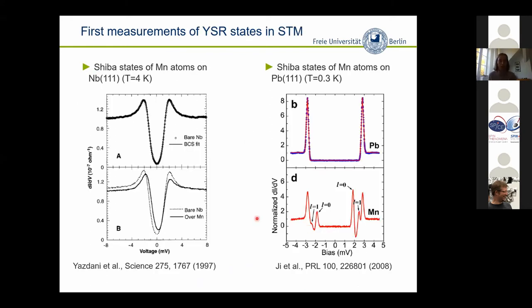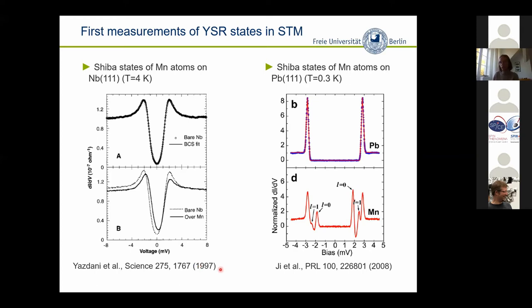We are not the first to measure Yu-Shiba-Rusinov states on single atoms — it dates back more than 20 years. Ali Yazdani and the Eigler group looked at manganese atoms on a niobium surface, using a metal tip at 4 K. Measuring on the bare superconducting surface gives an expression of the superconducting energy gap and the onsets of coherence peaks. When measuring on a manganese atom, they found an asymmetry and a slightly smaller gap — even given the rather poor energy resolution from today's perspective. They also looked at the spatial dependence, setting the basis for all the work done in recent years.